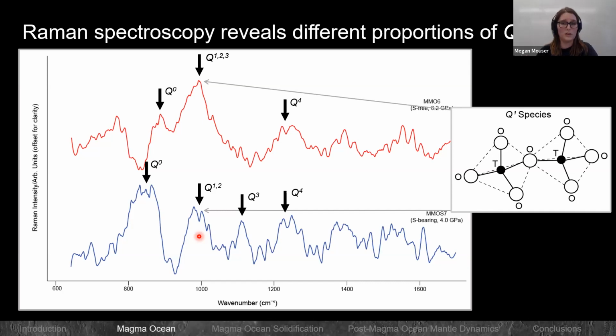And that probably largely comes down to compositional aspects of it. Maybe it's the reducing nature. Probably sulfur plays a big role in this. There have been some previous studies that suggest that when you have sulfur in the system, it could change the stability fields of minerals like forsterite and enstatite. So perhaps we're seeing some effect of that here. But at least we're able to confirm that what we're seeing within the viscosity data is this difference in the polymerization with the Q species.